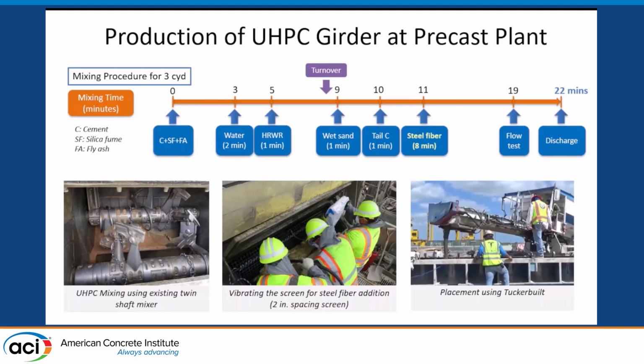We had to add these by hand, so it was a manual job that we did. We did follow some of the guidelines coming out of the PCI study, which was the idea of using a screen over the mouth of the mixer so that we could pour the fibers on top of that screen and then vibrate them into the mixer, and that worked well.